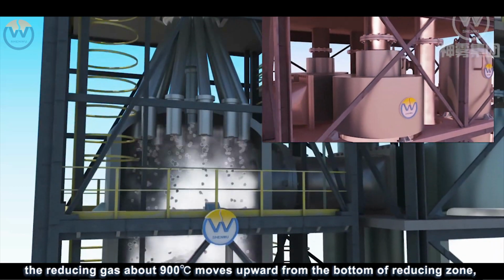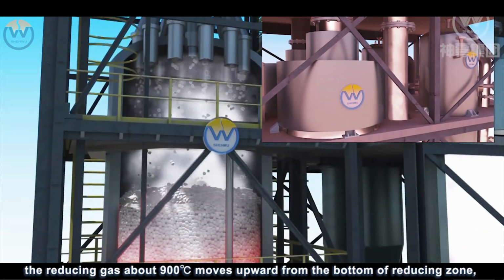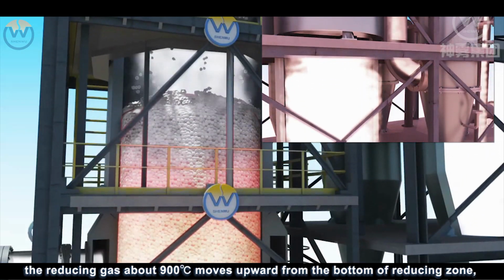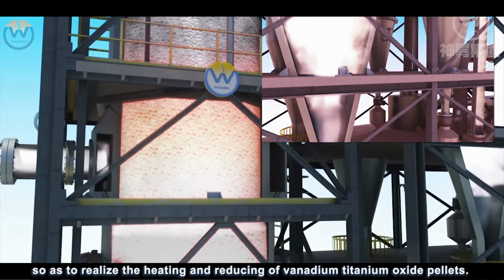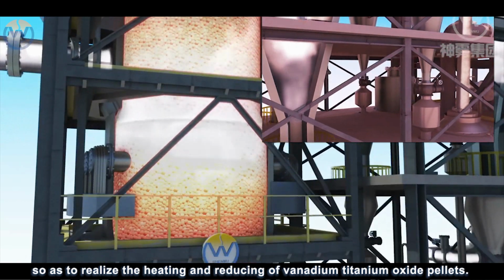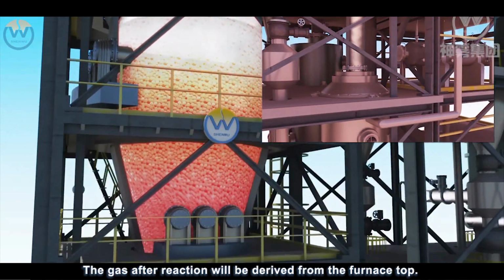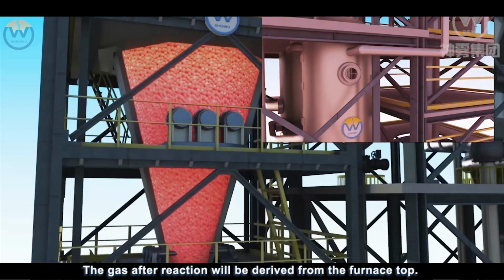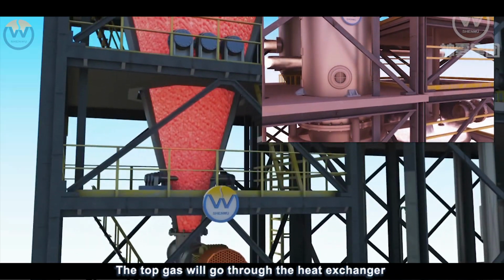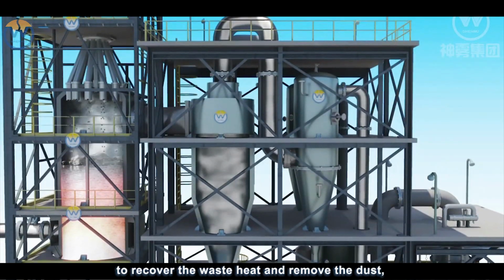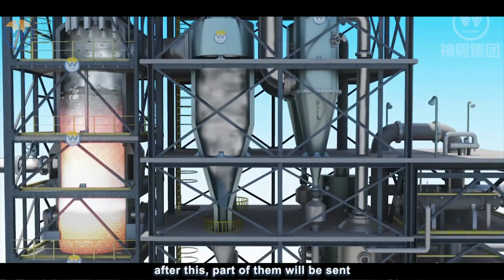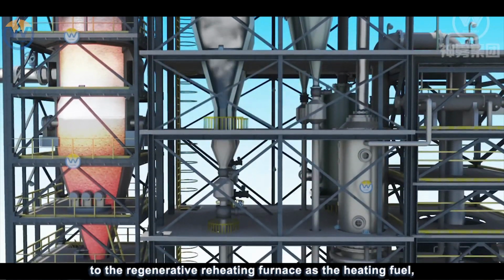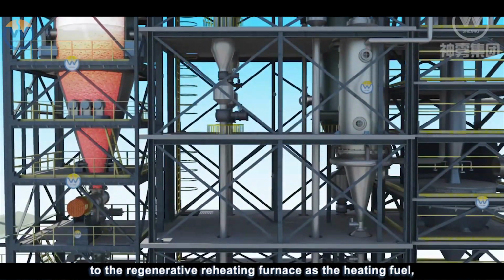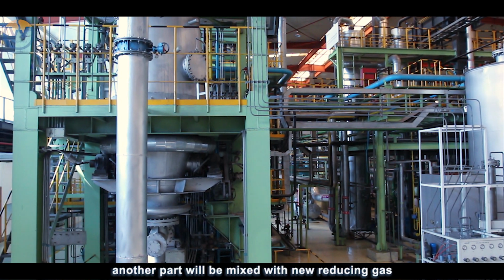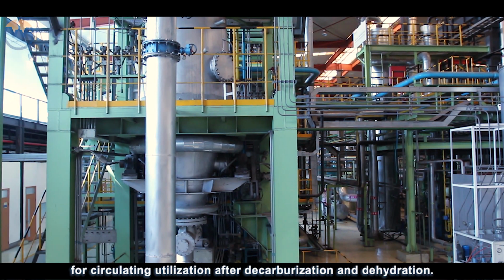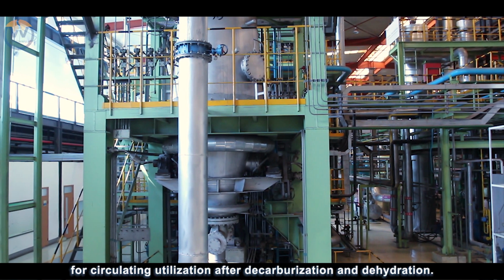The reducing gas, about 900 degrees centigrade, moves upward from the bottom of reducing zone, so as to realize the heating and reducing of vanadium titanium oxide pellets. The gas after reaction will be derived from the furnace top. The top gas will go through the heat exchanger to recover the waste heat and remove the dust. After this, part of them will be sent to the regenerative reheating furnace as the heating fuel. Another part will be mixed with new reducing gas for circulating utilization after decarburization and dehydration.